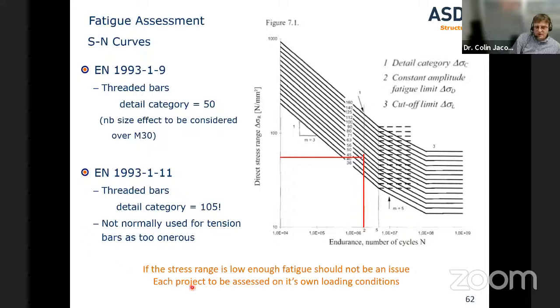But strictly speaking, if you went to EN 1993-1-11, the tension member code, they state a detail category of 105. And if you're testing and your detail category is 105, that's a very onerous test and very hard to achieve on a threaded tie rod. So our experience is that most engineers will not use this part and they would stick to just the 1993-1-9 and detail category of 50.